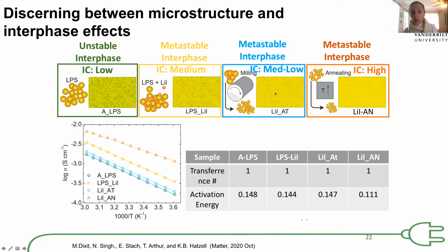To change the microstructure, we looked at milling our samples to create smaller particle sizes, so higher packing densities. And we looked at a subsequent annealing process, again, to improve density. What we saw was that our sample that had been annealed had the highest ionic conductivity, whereas our system with the metal, the unstable interface, had the lowest ionic conductivity, and these two were in the middle.